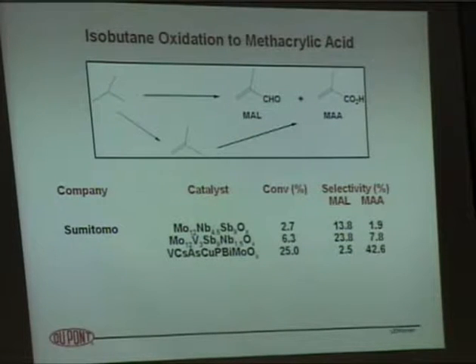Isobutane is a tougher molecule to oxidize. We've actually spent some time ourselves looking at this reaction. Isobutane today usually goes through isobutylene or tertiary butanol, which is then oxidized to methacrolein, and then in a second step to methacrylic acid. Sumitomo has most of the patents in this area that I've found. There's still a long way to go here, but recently they've been able to get the conversion up to about 25% with this molybdate-based catalyst system, and a selectivity of around 45% to methacrolein and methacrylic acid. So still a ways to go, but in the last 3 or 4 years, great advance in conversion while keeping the selectivity reasonable.